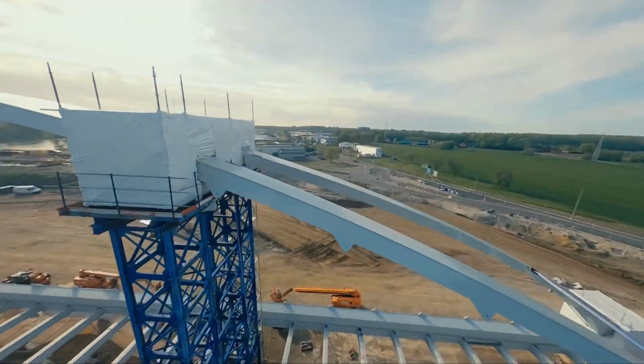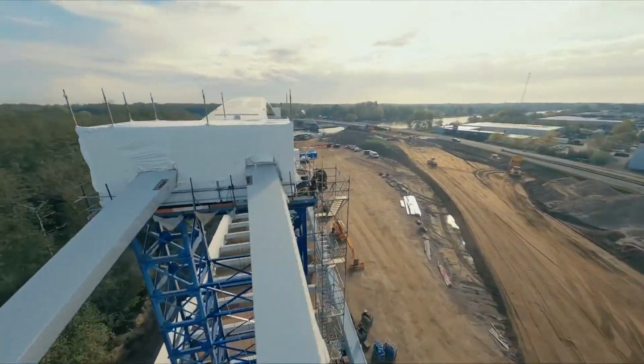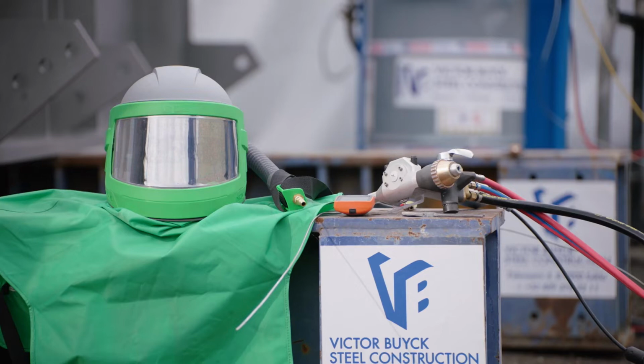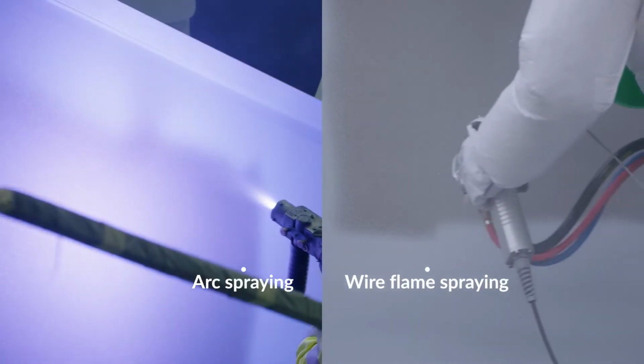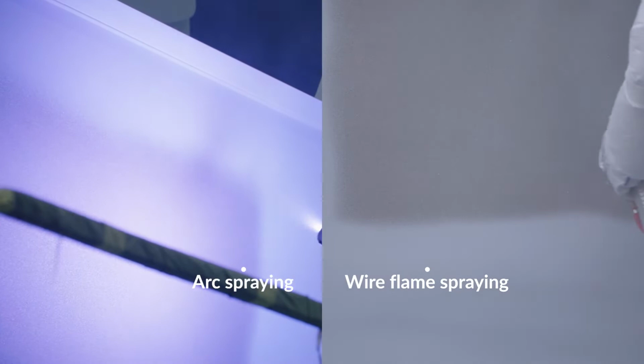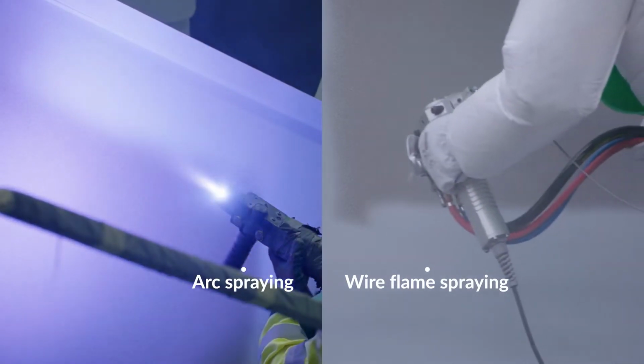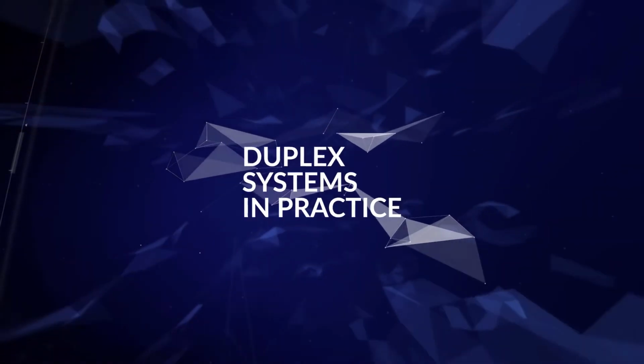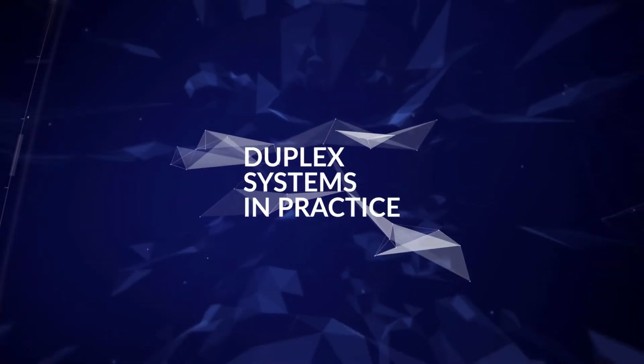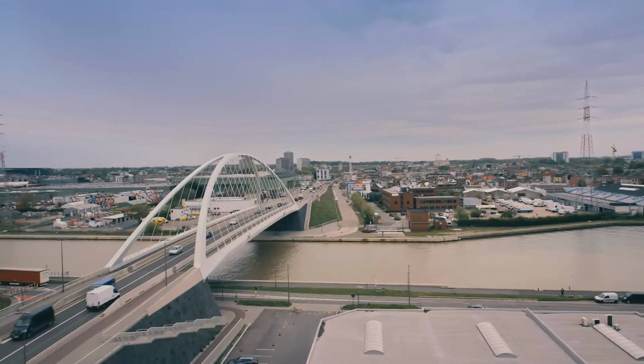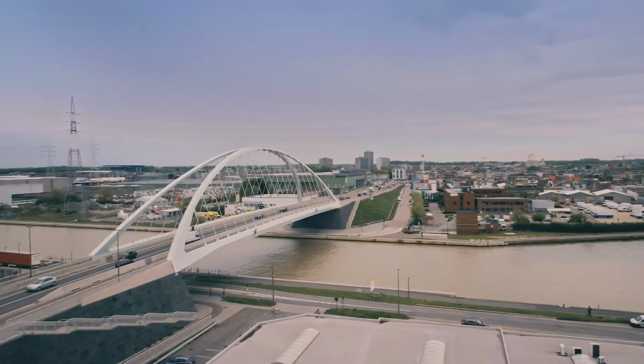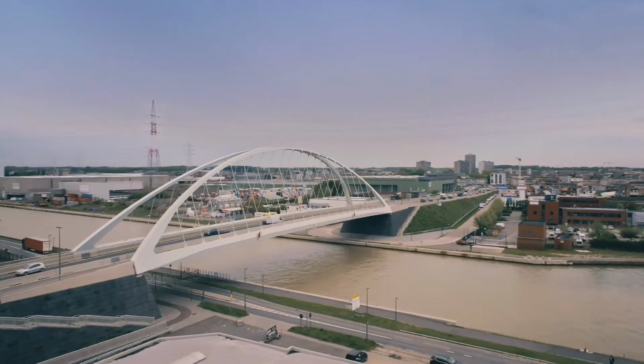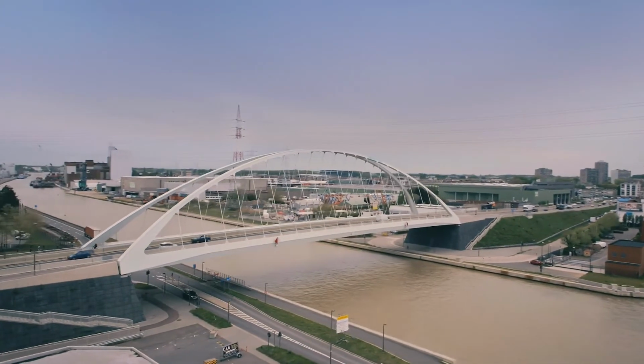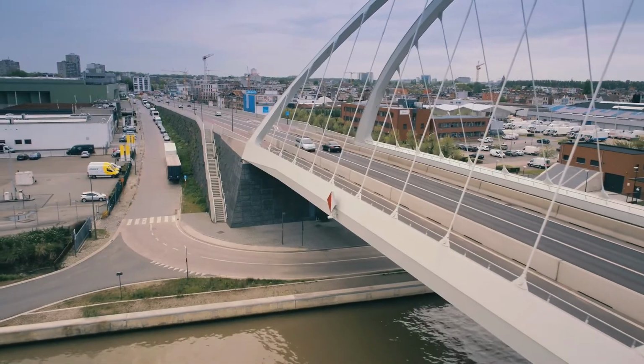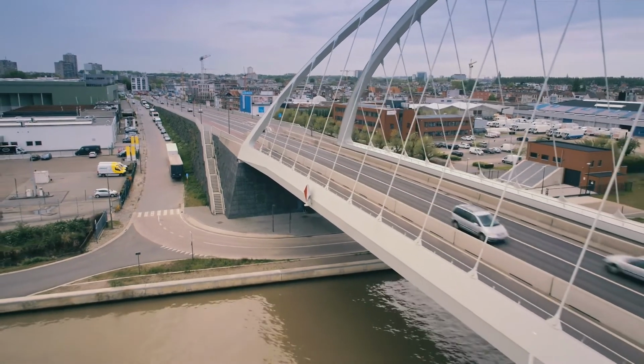Flame spraying equipment is often preferred at the construction site of a bridge because it's more mobile. The coating quality of both systems is comparable, and both systems can be used for the same construction. As an example, let's look at a bridge crossing the Albert Canal in Belgium. Here, a duplex system is applied. The thermal sprayed zinc aluminum alloy consists of 85% zinc and 15% aluminum and is finished with an organic top coat.